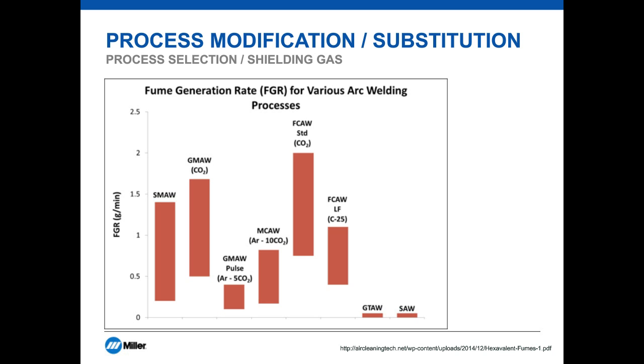Solid wire gas metal arc welding tends to be relatively low fuming, especially if pulse transfer is used with high argon shielding gas mixtures. I'll talk a little bit more about that later on. There are a variety of flux and metal cored welding products, some of which are designed specifically to be low fuming, and others that may target specific elements in the fume, such as manganese or hexavalent chromium.